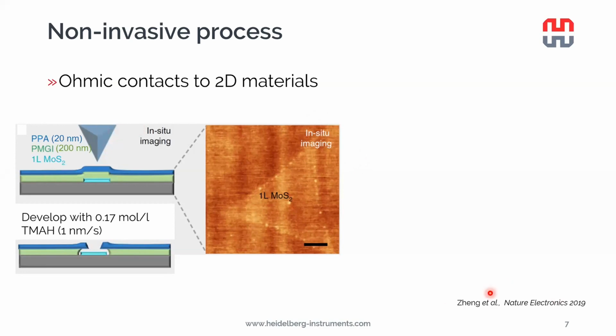What was done in this paper from Zheng last year was they used a layer of 200 nanometers of PMGI. PMGI is our typical lift-off resist of choice, coated with 20 nanometers of PPA, and underneath one layer of MoS2 grown by chemical vapor deposition. After that, the sample was imaged using the NanoFrazor tip, and the flakes were still very nicely visible through the entire stack of resists. And they could carry out a nice overlay of electrodes, and they removed the resist on desired locations. And the PMGI was developed with a diluted TMAH at 1 nanometer per second develop rate. Low develop rate is important so that we can control the undercut accurately.